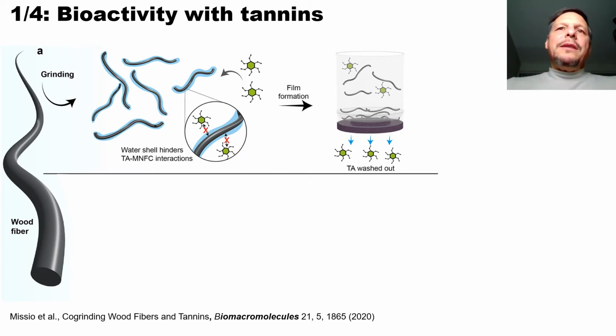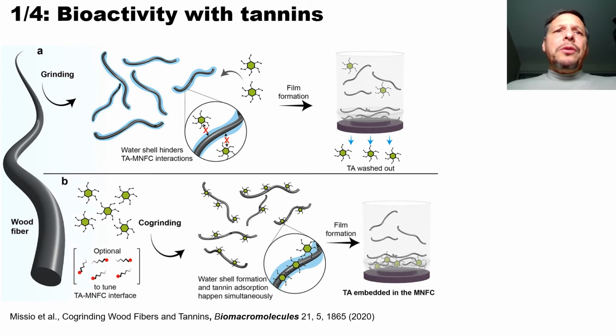However, one thing that we notice is that the tannins have difficulty staying with the fibrils. They will be washed out. They won't be retained. And for that reason, what we have used as an optional pathway is to combine this also with surfactants. So by using a small amount of surfactants, we can have a better binding of the tannins on the fibrils, and then we can produce a paper product that can exhibit the effects of the tannins, and why not, those of the surfactants that we're adding in the process.